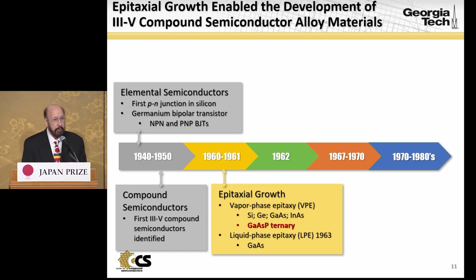In 1960-61, because of the interest in controlling doping in silicon and germanium, vapor phase epitaxy was developed over this one-year period for both silicon and germanium, but also gallium arsenide, indium arsenide, and importantly, the ternary alloy gallium arsenide phosphide by Nick Holonyak at General Electric at the time. And that was used to make the first visible red light-emitting diodes. Also, 2 years later, in 1963, liquid phase epitaxy was developed for gallium arsenide. So this work sets the stage for the next development.